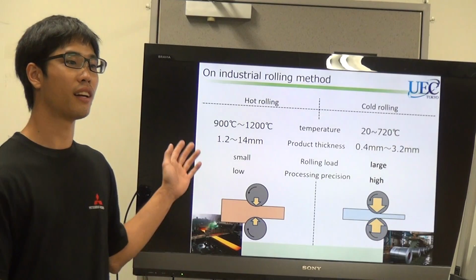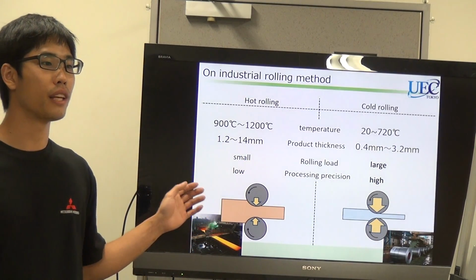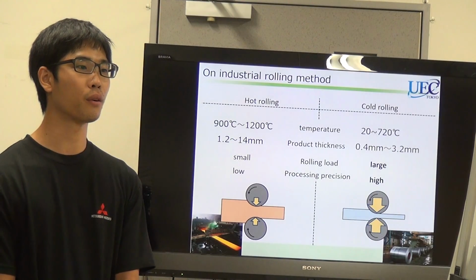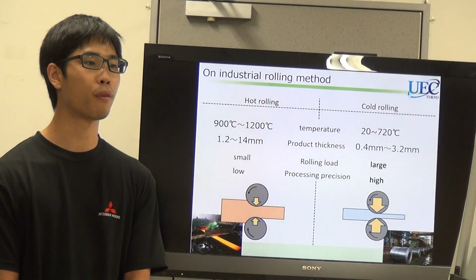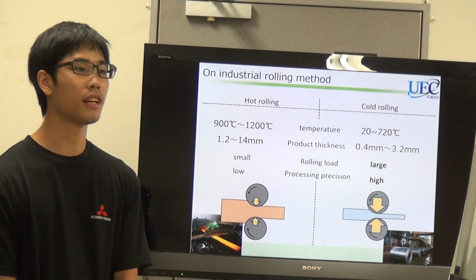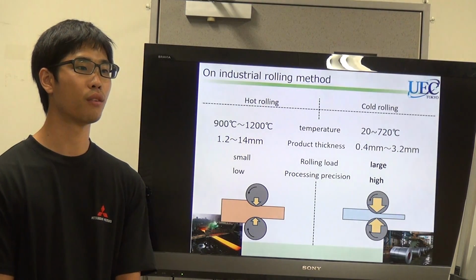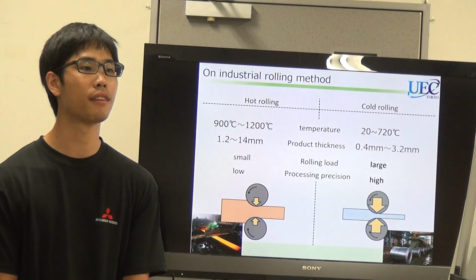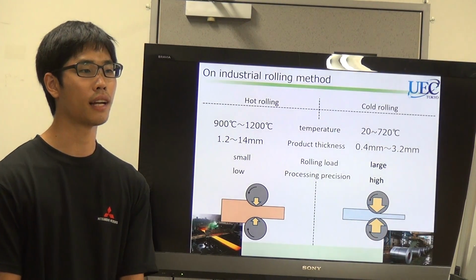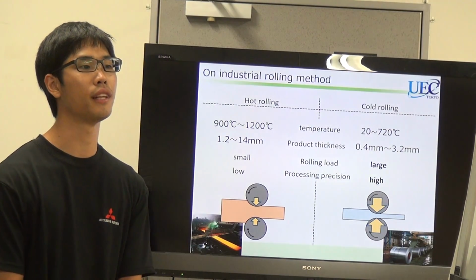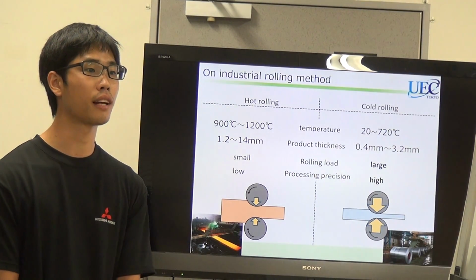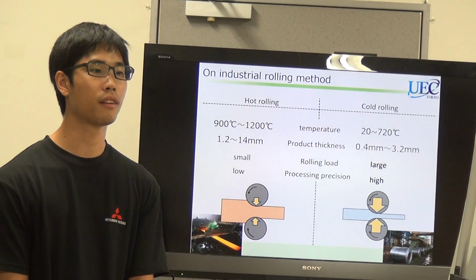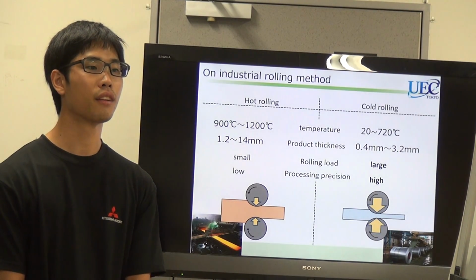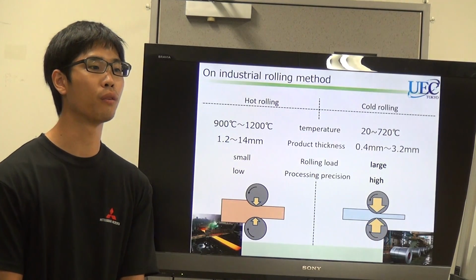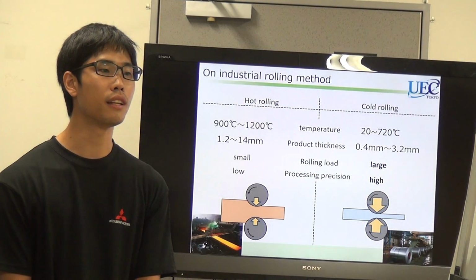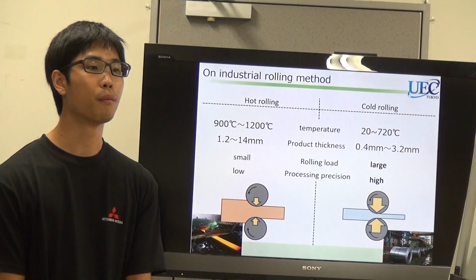As shown here, there are two types: hot rolling, in which rolling is performed while the metal is hot, and cold rolling, in which rolling is performed at low temperature. Hot rolling is done at 900 to 1200 degrees Celsius, while cold rolling is done at a temperature as low as 720 degrees. Hot rolling is characterized by the fact that the steel sheet is so soft that the rolling load is relatively small, and it is possible to process a great thickness.